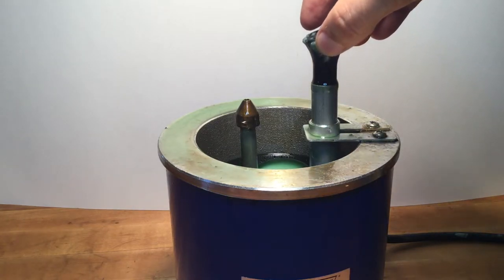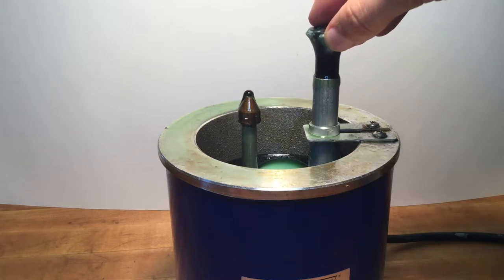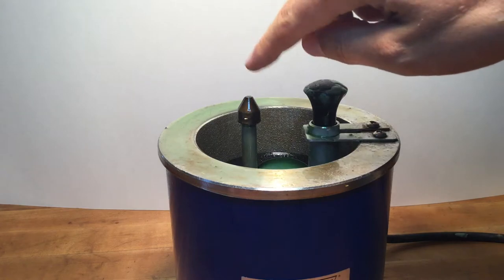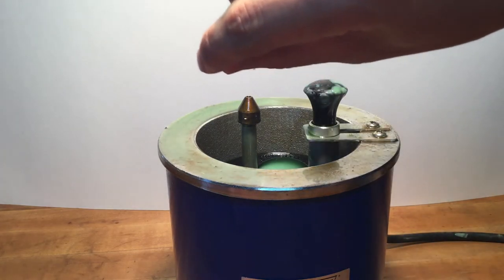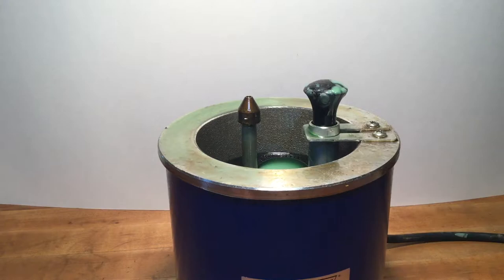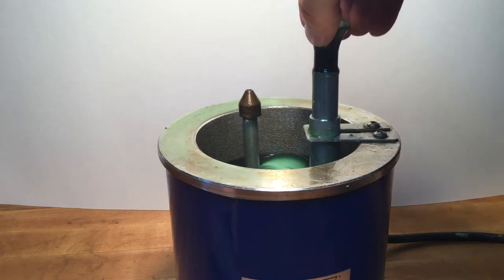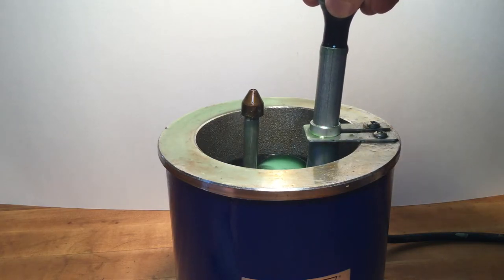And you do not want your wax coming out really hot, boiling hot. So when you inject, you want to make sure that it's coming out translucent. You can see through it, but there's not a lot of air bubbles. If it's boiling in there, it's just going to end up with porosity in your part, and that's more work than you really want.